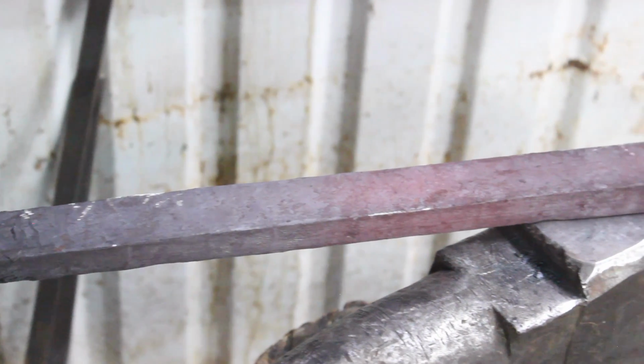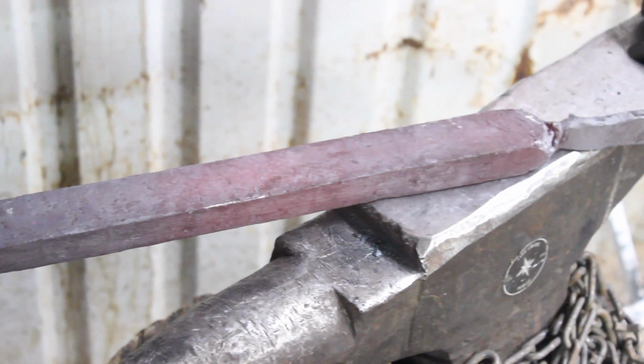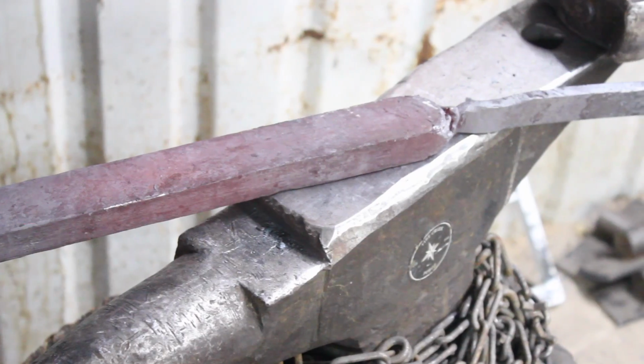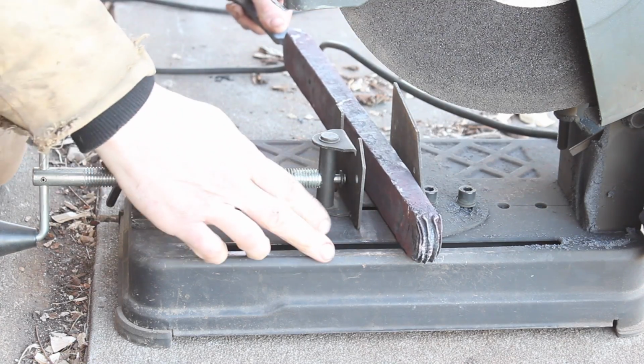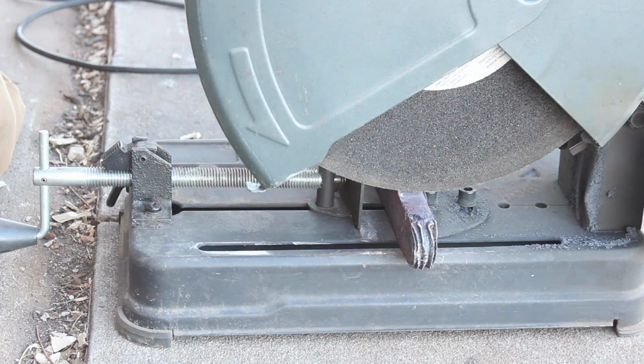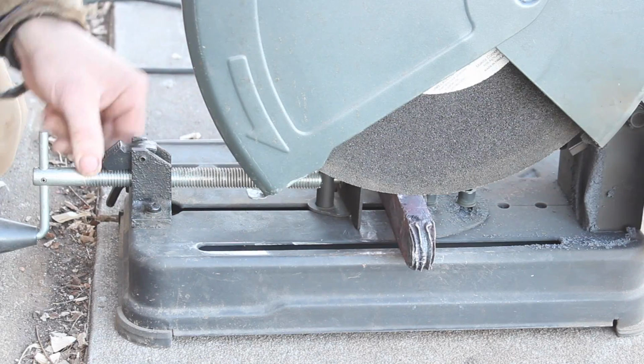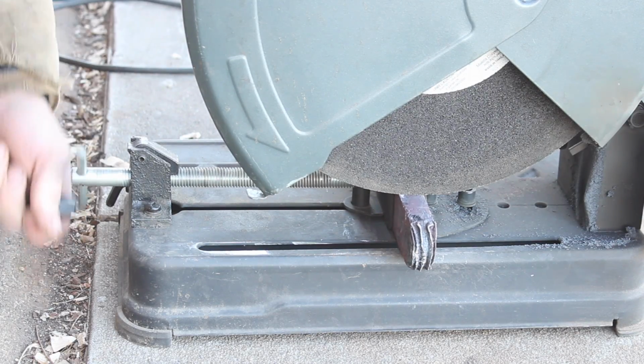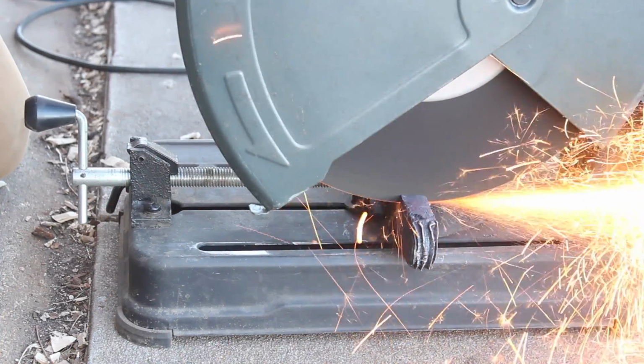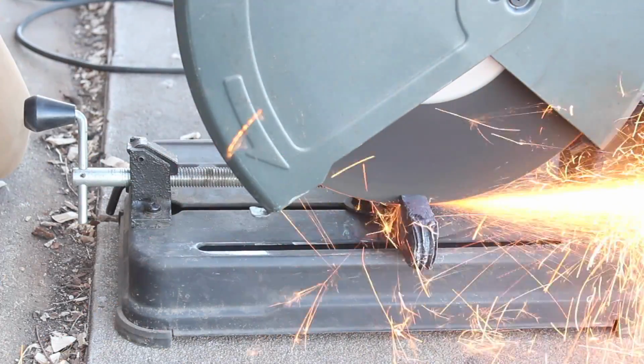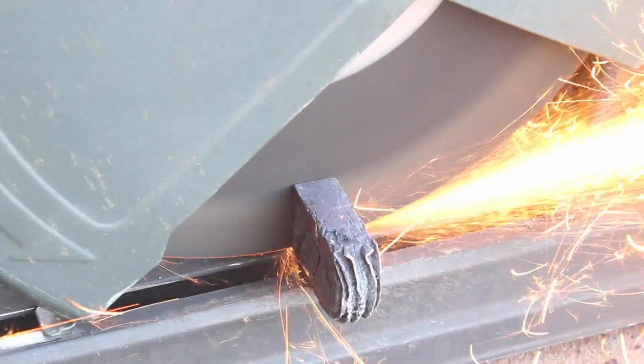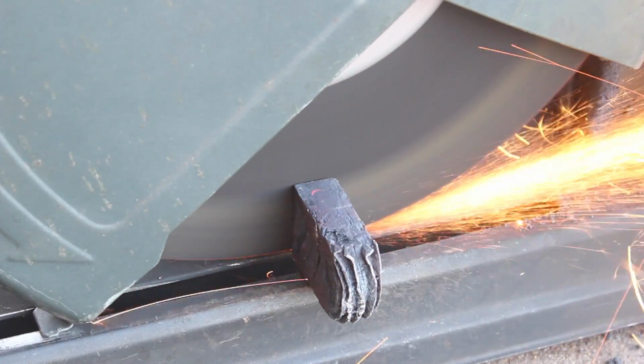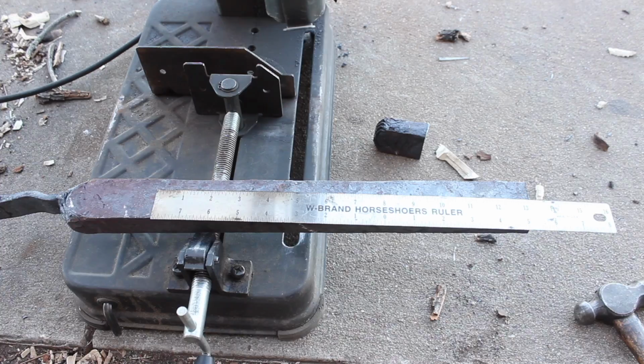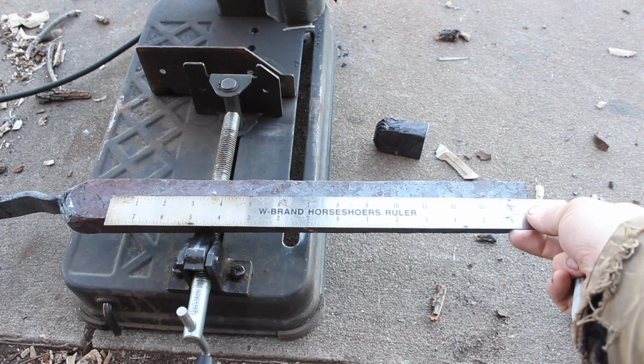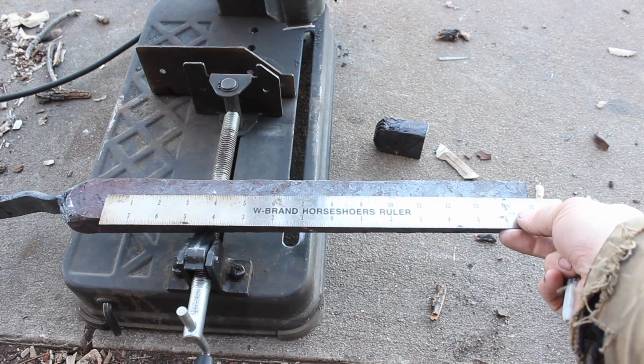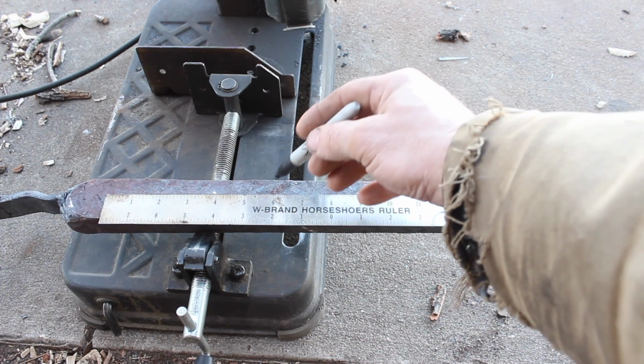So there we have it. It's down to, like I say, about 1 inch thick, and the main thing I'm looking for here is the length that I need to cut it up into the pieces I need to restack and re-weld it for the desired layer count. So we started with about 41 layers, not counting the ends that are going to be back up against each other. In this case, I had a little more of a cruddy end than normal, so I had to cut off more of that. But I'm going to save that, and I can use that in a future project.